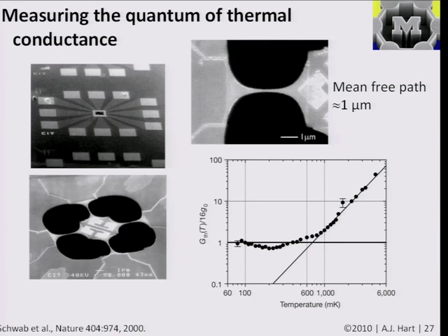And people have actually measured this recently. It's a really complicated experiment where you can only see the results at low temperature. But what they've done is they've fabricated this small structure. So you've got pads connecting, and then if you zoom into this middle region, closer and closer, eventually you get to this structure where they've got different connections. And this is, I think, a silicon nitride bridge, and at the minimum point, it's about 300 atoms wide. And that, they figured out, supports only 16 different vibrational modes.